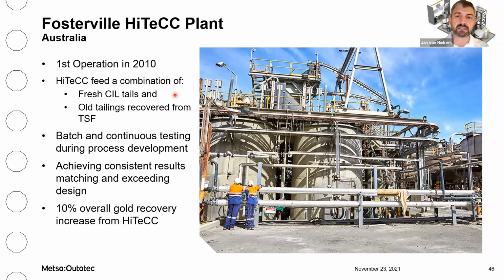They evaluated all the standard processes to try and mitigate this preg robbing, including blinding agents, as well as trying to remove the organic carbon before treatment using flotation or gravity, but nothing really addressed the situation or was associated with too high gold losses. So then they developed the process themselves following quite an extensive process of batch and continuous testing. But really the process is achieving very consistent results, matching and or exceeding their design. And they can get a 10% increase in overall gold recovery from the HiTeCC process.